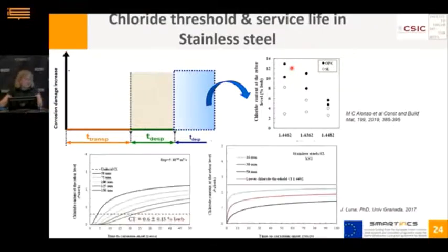But again, if the service life is calculated, as explained before, for the conventional rebar steel reinforcements, considering one type of concrete with one specific transport of aggressive agents, clearly the initiation of corrosion can be expected in a relatively short time. But if stainless steel is employed, the time for corrosion initiation is significantly increased due to the increase in the chloride threshold with this protection method.